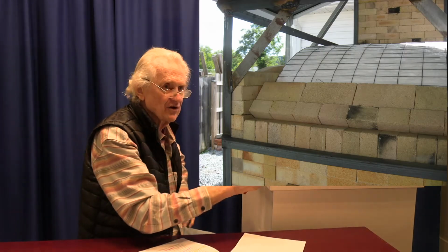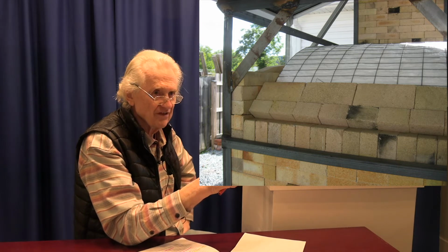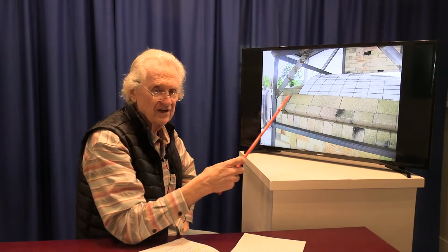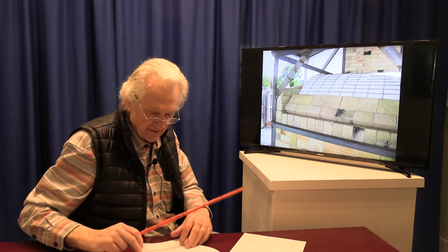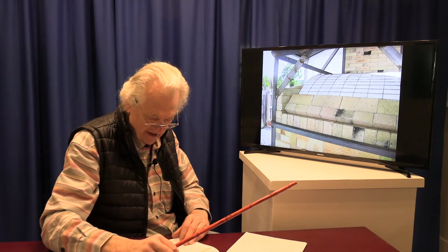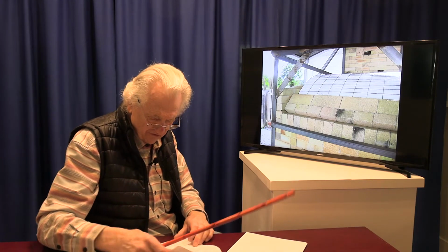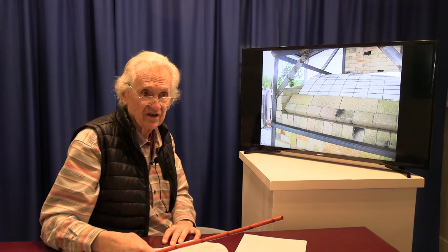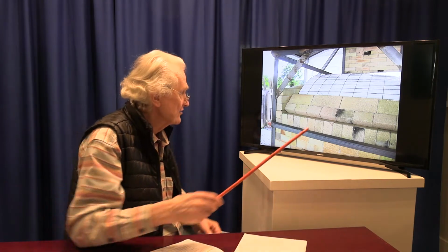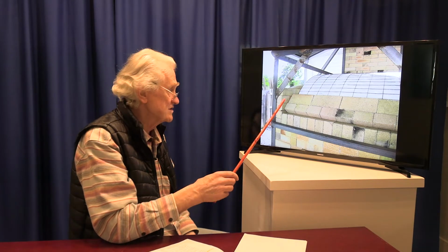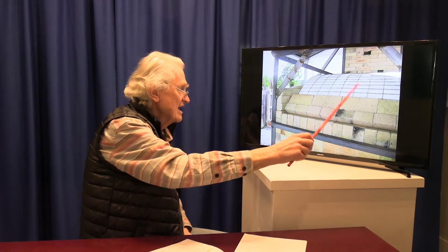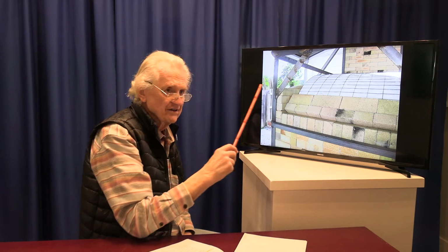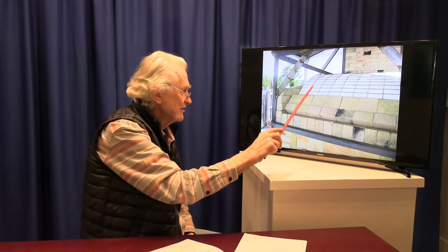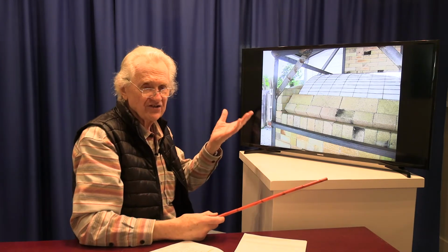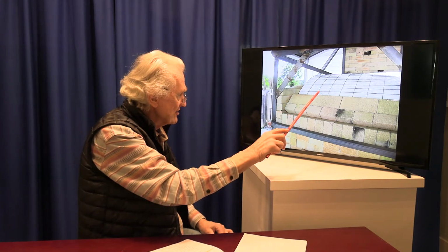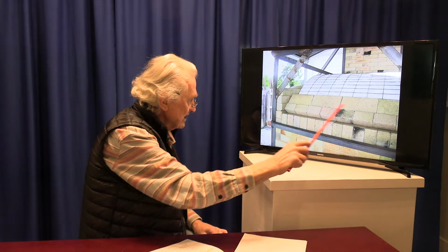So once we had done that, on top of the dried slip, we put down 2 layers of insulating blanket. This was basically Fiberfrax blanket, I think, inch-thick blanket. This was Unifrax Dura Blanket S, as in Sam, 6-pound cubic density. This was also material that we salvaged from the previous kiln. We put down 2 layers of blanket, and then we covered it with a layer of welded fencing. These are 2-inch by 4-inch openings for scale. And that's just to hold the blanket in place, basically. And then we anchored the blanket and the fencing with an extra layer of bricks on the end.